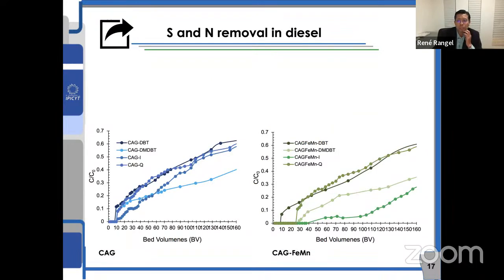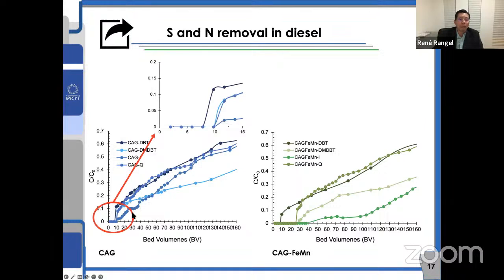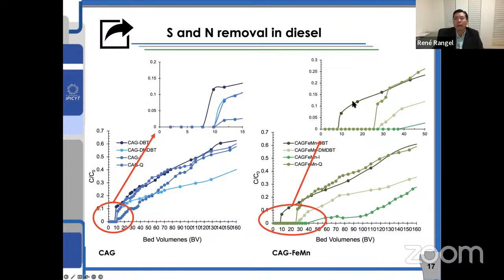Here in these graphs, I don't want you to see all the numbers. I just want to make an example that when we use only granular activated carbon, these are continuous experiments, breakthrough curves. So we can see that in the axis we have the bed volume. When we have only granular activated carbon, the initial breakthrough can occur, for example, at 10 bed volumes. But once we modify the carbon material with metal oxides, you can see that the sorption capacity increases a lot.